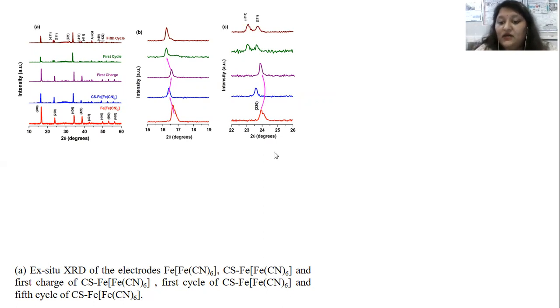It may be noted that the sodiated and bare electrodes have a similar XRD profile of a well crystallized cubic structure, which is similar to the powder XRD presented. Correspondingly, the sodiated PBA at the end of the first charge belongs to a well-oriented cubic structure, similar to the electrodes before cycling. The closer view of ex situ XRD depicted in B and C confirms the phase transition.